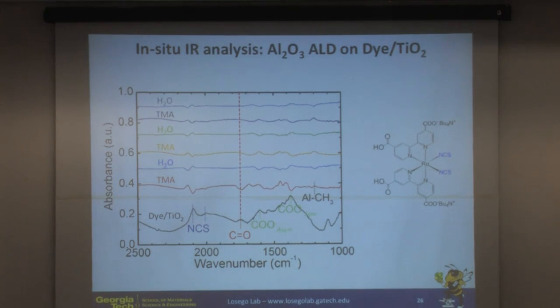carboxylic acid groups, and within a single exposure to our TMA, we see a removal of those sorts of stretches in the material. The thiocyanate group, we see this back and forth motion, so we're somehow modifying the thiocyanate with each precursor co-reactant cycle. And then these COO stretches, we actually also see, you'll see up, down, up, down, up, down, and then sort of the reverse of that on the other side.